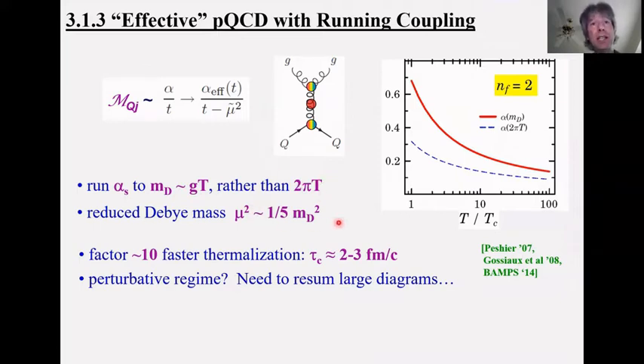So in addition, the Debye mass may be much smaller than what you think if you do a hard thermal loop calculation and match the soft to the hard part. Now, what you get out of such a calculation is that indeed the thermalization time becomes much faster, by about a factor of 10 over the baseline perturbative estimate, down to 2 to 3.